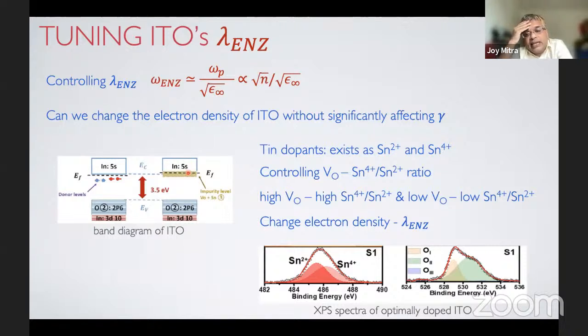So how do we control the number density? The easiest way of controlling the number density is to tune the tin oxidation ratio. The tin actually exists in two oxidized states, tin 4+ and 2+. If you manage to change the oxidation state of tin, you manage to control or change the number density in the system. And after a bit of survey and initial work, we realized that we can do that by controlling the oxygen vacancies in the system. If you have a large number of oxygen vacancies, you have a very large tin 4+ to 2+ ratio. A low oxygen vacancy gives us a low 4+ to 2+ ratio, which essentially means the conductivity is going to decrease.